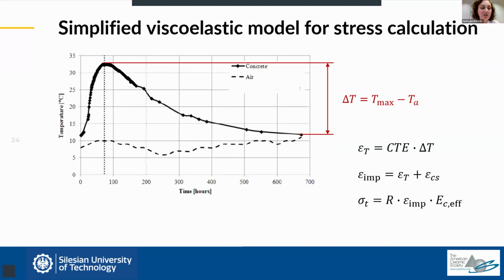I wanted to remind you, we have a phase of rapid temperature increase when the hydration heat prevails, and then we have subsequent cooling when we deplete the hydration heat and the wall starts to cool to the ambient temperature. And this cooling phase is responsible for production of tensile stresses, as I showed in this more complex analysis. So in our simplified approach, we only consider the thermal strain, which is caused by this temperature decrease.